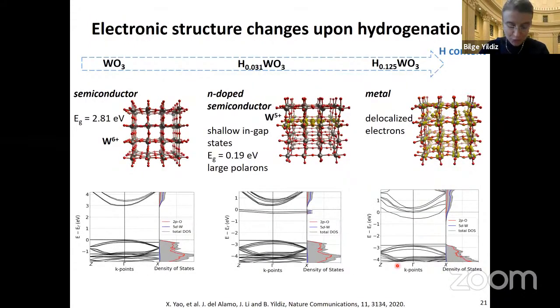So complementary to those is the change in electronic structure that we could probe theoretically. To start with, tungsten oxide is a semiconductor with 2.81 eV band gap. With a small amount of hydrogen insertion, we see the formation of in-gap states, shallow in-gap states that can serve as N-type donors, and they take the form of large polarons.